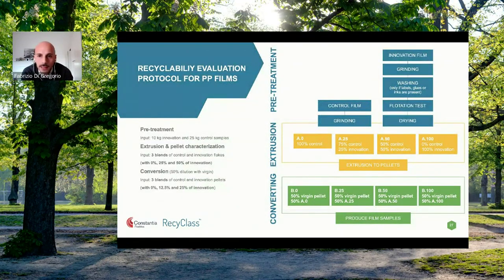As I said, behind the guidelines there are testing protocols. All the protocols are available online, and they are standard procedures resembling the industrial-scale mechanical recycling process. So also for polypropylene flexible films, you can see that we have three main steps. Pre-treatment steps, where the flexible film is first ground and washed. We apply flotation to separate by density all the separable material. And then different blends of materials are prepared in order to extrude the material and then analyze the pellets.